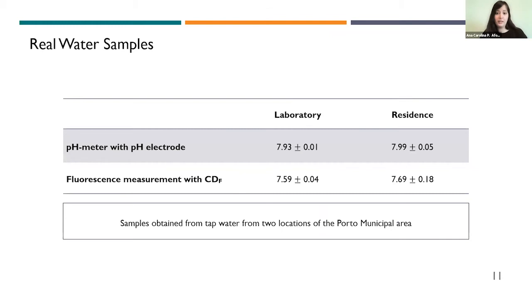To further validate the suitability of this carbon dot as a fluorescence pH nanosensor, we used it to determine the pH values of 2 real water samples by applying the previously shown logistic fit. The results show that pH values obtained with the carbon dot agree with those obtained with a standard pH electrode-based method, and so validates its use as a fluorescence pH sensor.